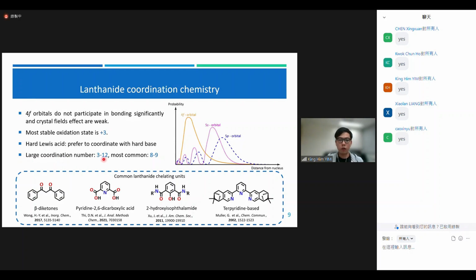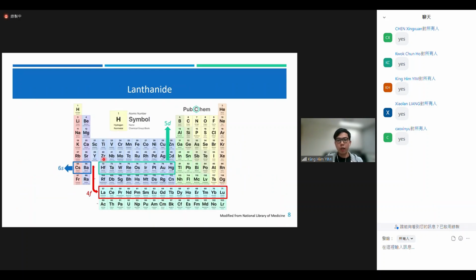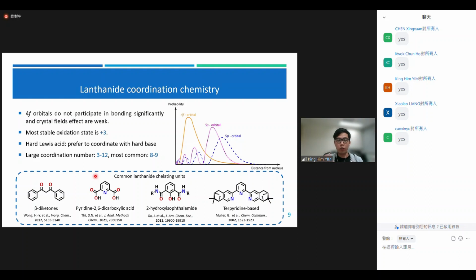So going back to the periodic table, you can see it's located in the 6th period. That means the lanthanide atom is very large, so it can coordinate with a lot of ligands compared with transition metals. So it accommodates large coordination numbers from 3 to 12, and the most common by far is around 8 to 9.